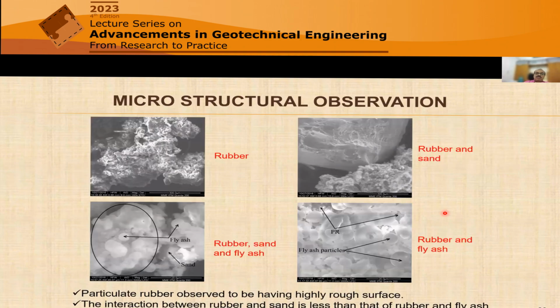Before going into that, we did a bit of microstructural study on this rubber sand mixture. We also tried to benchmark with fly ash. We saw that particulate rubber was observed to have a highly rough surface, because it's shredded in a workshop, so it's not a very smooth surface. The interaction between rubber and sand is much less compared to rubber and fly ash. In fact, we did a follow-up study with direct shear on rubber and fly ash instead of rubber and sand. There, the reduction in friction angle is actually negligible.